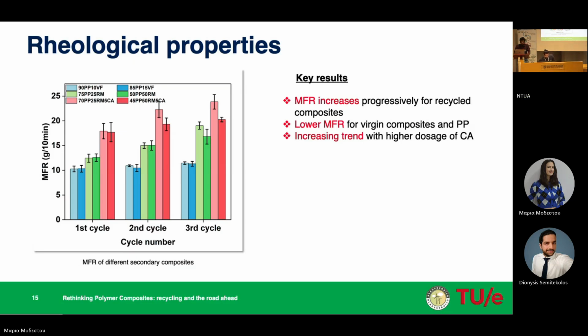the higher the fiber loading is, the lower would be the melt flow rate, because the fiber itself acts as a barrier which will hinder the chain mobility of the polymer matrix. And also, the increase in melt flow rate for recycled composites can be attributed to the thermoset residue that might actually hinder the entanglement of polypropylene chains and thereby decrease the viscosity of the polypropylene.